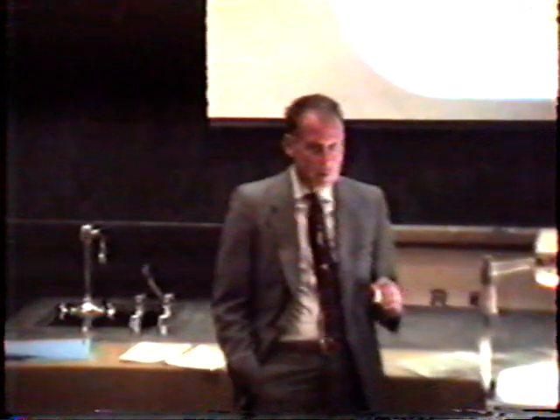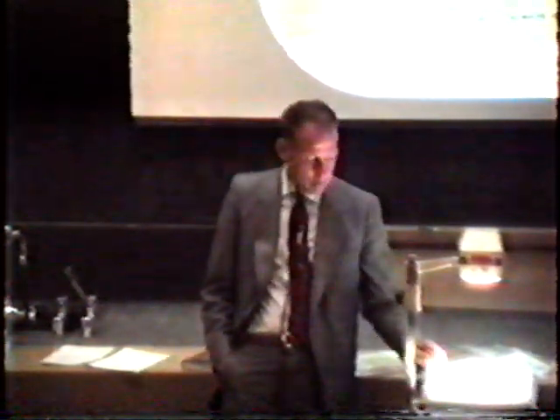and the large peak we assigned about 10 to the 14th. Now to do this right, we would have had to have deuterium oxygen mixtures with known amounts of helium. That would have been the only way to really quantify it. But that's the best we could do at the time, to say that we had large amounts, medium amounts, or small amounts, which correspond to 10 to the 12th, 10 to the 13th, or 10 to the 14th. So within the order of magnitude is about all we can say, and within the order of magnitude, the amount of helium we found was about the right amount based on the amount of excess heat we were getting.